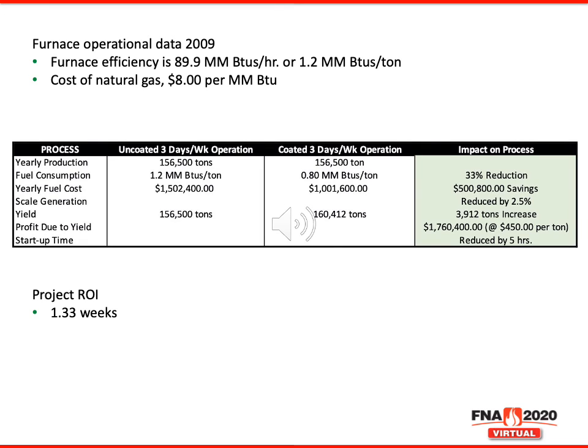With the installation of the veneering process complete and the furnace back in operation, let's review the benefits of the newly coated furnace. Operating 3 days per week and producing approximately 156,000 tons per year, the fuel consumption was reduced from 1.2 million BTUs per ton down to 0.8 million BTUs per ton of steel produced, or roughly a 33% reduction in fuel consumption. At a cost of $8 per million BTU, their yearly fuel cost was reduced from $1.5 million to $1 million per year for an annual savings of $500,000.